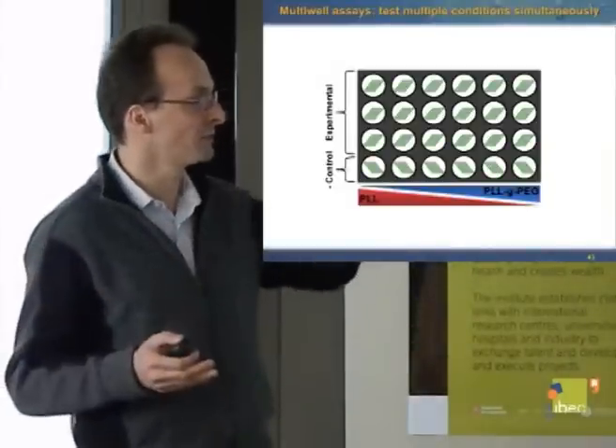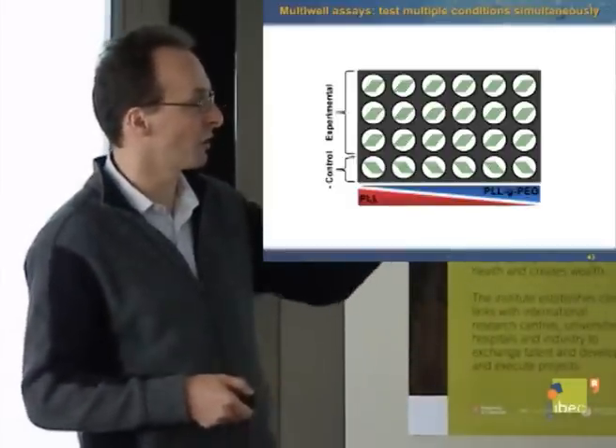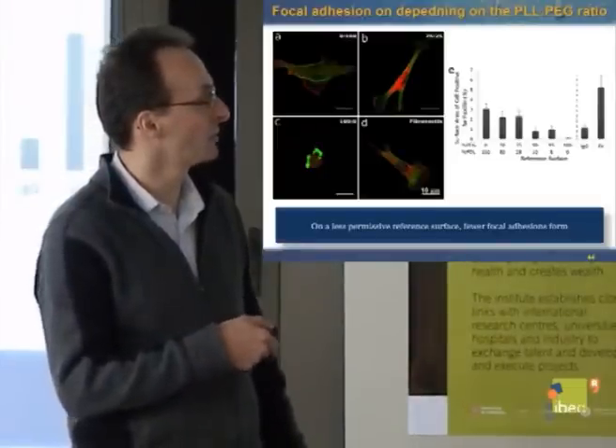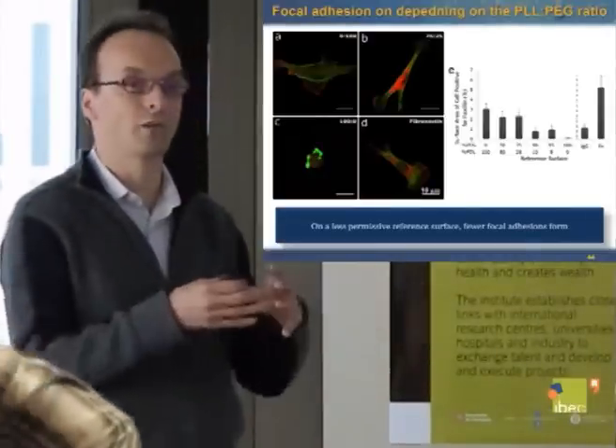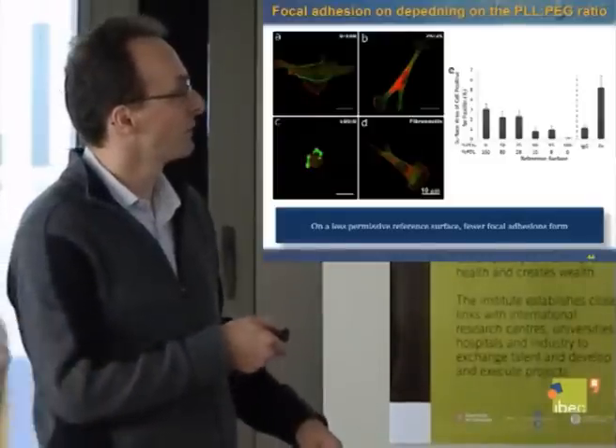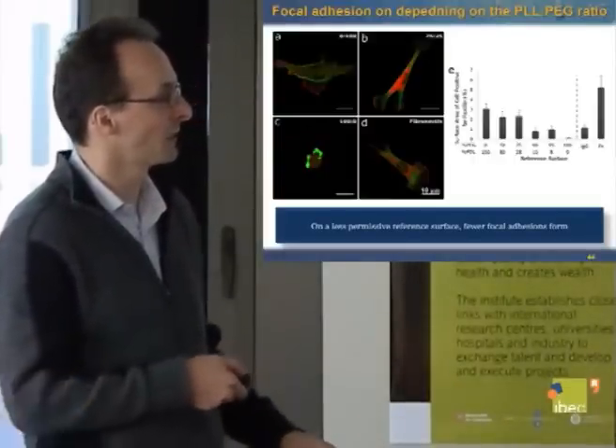To do these experiments systematically, we developed a well-plate array so we can pattern stripes with all combinations at once and do a number of tests rapidly. At the microscopic scale, 100% PLL shows well-developed focal adhesions and actin networks; pure PEG causes cells to round up and often die; at 75-25 you see a morphology that resembles a pure fibronectin surface — as expected, less permissive surfaces give less focal adhesion.